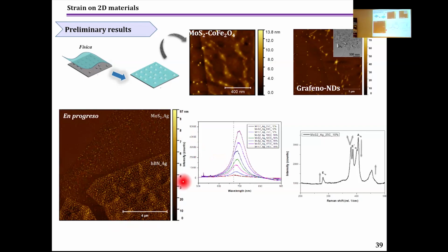This is, for example, one work on SERS, which is the enhanced spectroscopy using metallic particles. Here we have seen that this material, MoS2, which has potential application as an optoelectronic material, can have its properties tuned. The photoluminescence can be tuned by depositing silver onto its surface. So we obtain a shift in the optoelectronic properties, but also we can have switching of the Raman spectroscopy, which suggests that we are changing the electronic properties of the material.